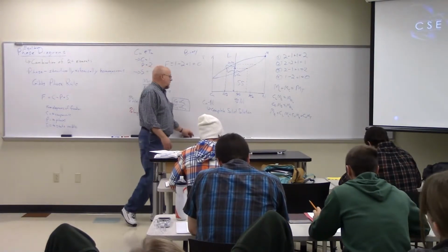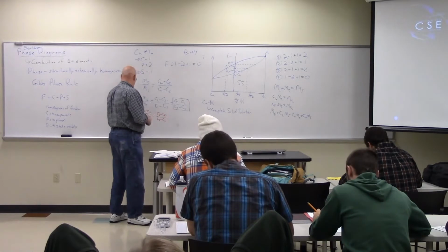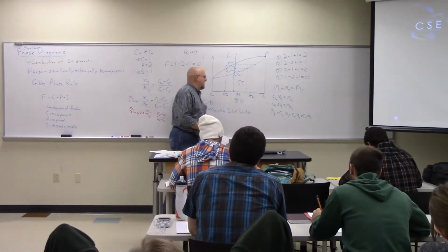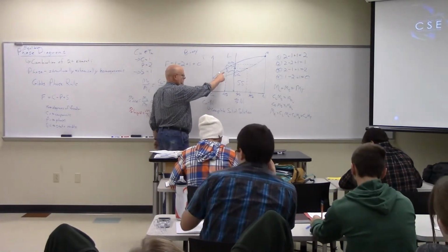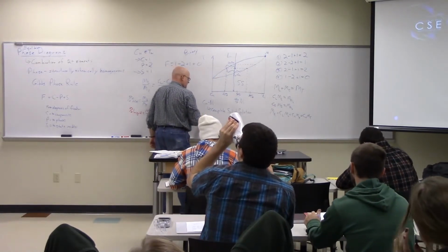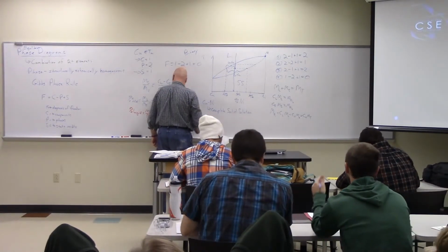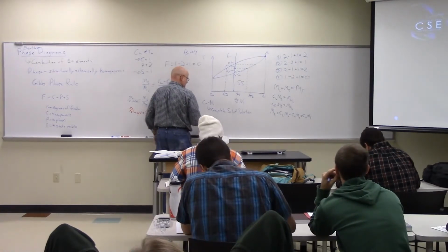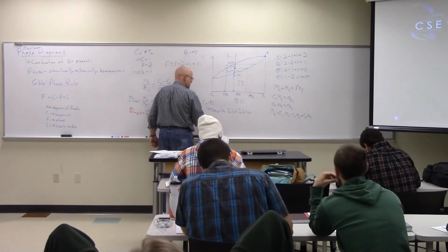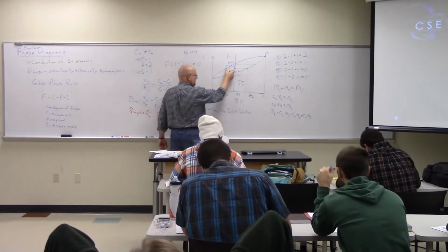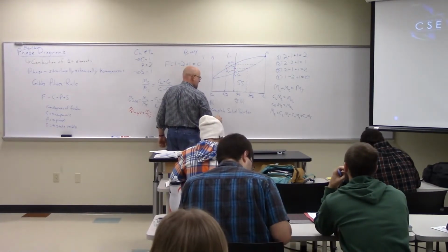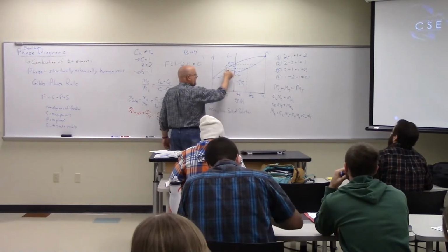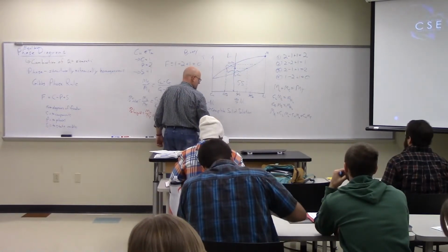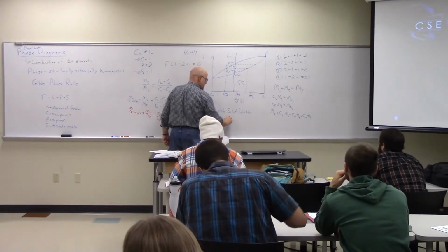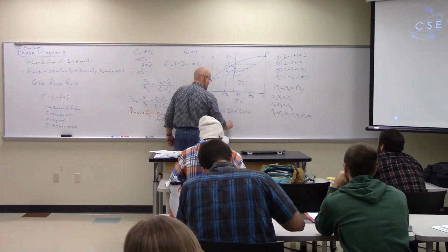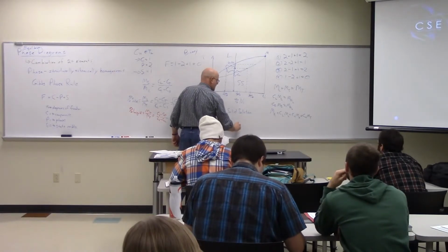So let's look at the example that I've drawn here. In this case, the percent nickel, I'm sorry, percent solid solution. Percent solid is this distance, 45 minus 25, divided by the whole thing, which is 65 minus 25. So that's 20 divided by 40, or 1/2.